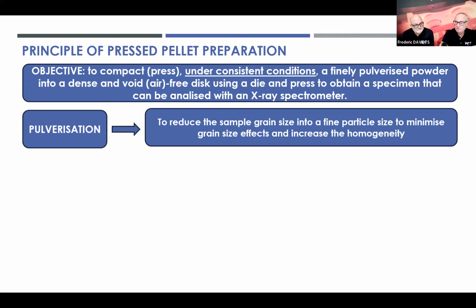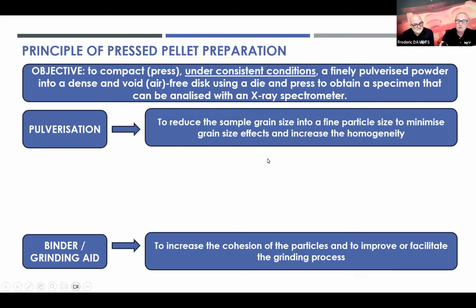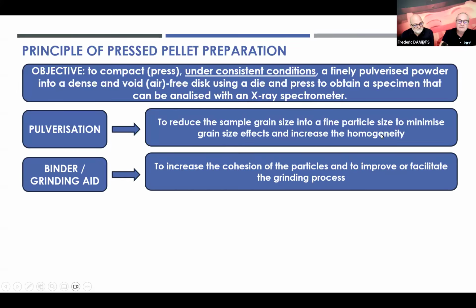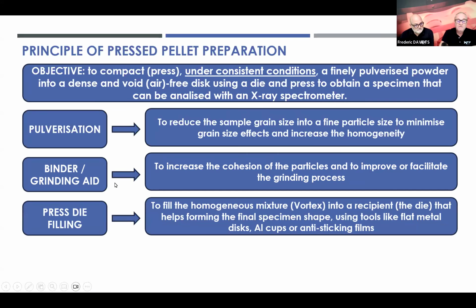So a first step is the pulverization, where we're going to reduce the sample grain size into very fine particles to minimize the grain size effects, and at the same time to increase the homogeneity. Then we're going to add to this fine powder a binder or maybe a grinding aid to increase the cohesion of the particles and to improve also the grinding process. Then we are going to fill this mixture into our press die, and the press die is going to give the shape to our sample. Depending on the amount of sample and the kind of sample, we may use a smaller or a bigger die size to create our specimen. And eventually we can also use tools like aluminum cups or anti-sticking films to help us prepare better quality discs.